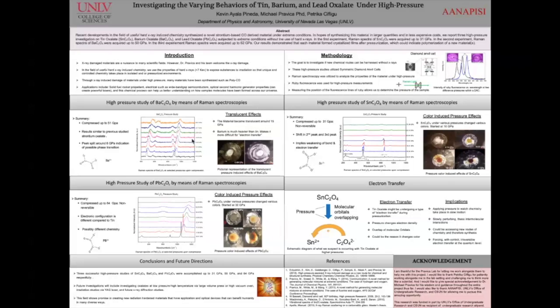So to get into my studies here, first I did barium oxalate, and I went up to 51 GPa. And only two important things came out of it. First, I noticed that this peak here split into two, and that could indicate a phase transition, or in other words, the crystal structure of the material just changed. Now, as a qualitative behavior, the material did become translucent around 15 GPa, that is, light started shining through it. And those are the two major findings I found for that study.